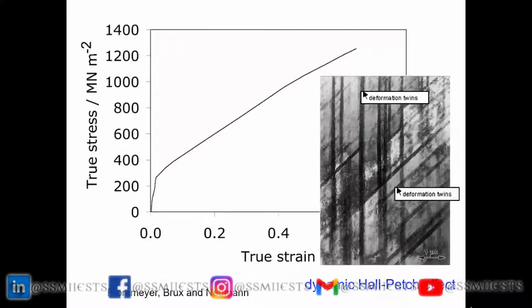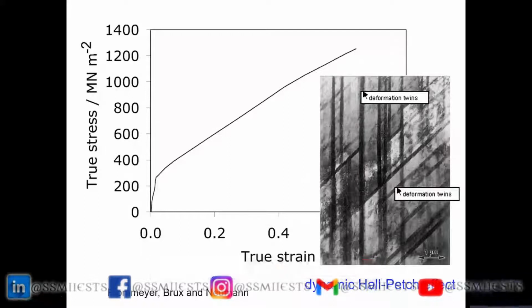And it starts off deformation by mechanical twinning. So here you see a transmission electron micrograph showing you extremely fine mechanical twins. This scale bar here is 1 micrometer. And what happens is that just as when we refine the grain size, we get a greater strength, these twins partition the austenite into smaller and smaller compartments as deformation happens, and therefore they produce strengthening by dynamically refining the grain size. So we call this a dynamic Hall-Petch effect, where the islands of austenite are divided into smaller and smaller sections by these twins. Okay, so this is the TWIP steel concept.